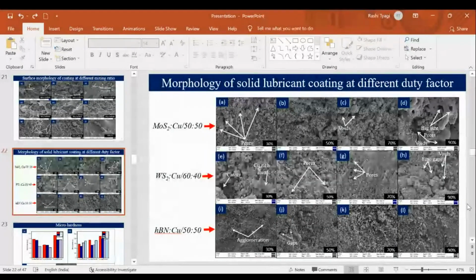Basically, process efficiency can be determined by duty factor. Why? Because when you use a duty factor higher than a particular level, arcing will take place. What is arcing? Arcing means the spark will not move from one location to another location. Localized deposition takes place, burning takes place, so coating will not be done.